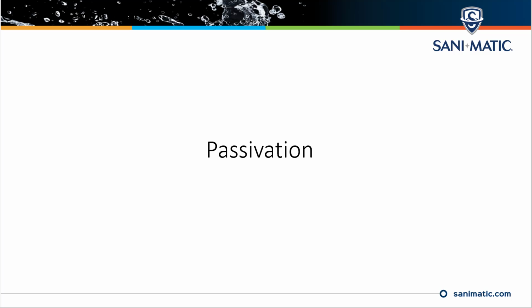There is a study, so the 24 hours I didn't just get out of the air. There is a study that was done, I believe by somebody in Germany. They were able to measure the angstrom level of the passive layer, and that's where my information came from. And in the biopharmaceutical industry, they do address that more precisely as to what the recommendations are. I think there it's a minimum of 48, but 24 is usually.